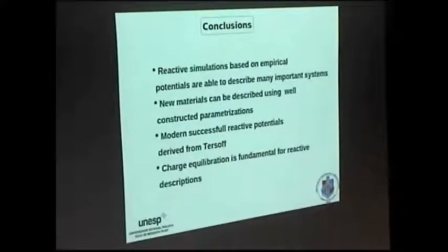And one important thing that I would like you to remember is that the Tersoff potential is the origin for many, many new descriptions that we have today. COMB potentials and ReaxFF potentials are based on Tersoff in some sense. And the charge equilibration is something that is really important and fundamental for nice descriptions.